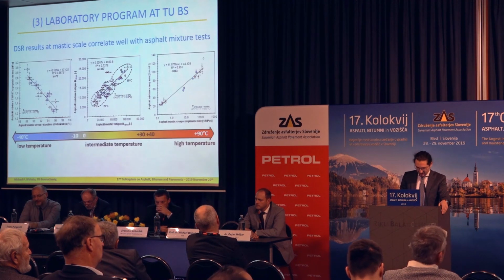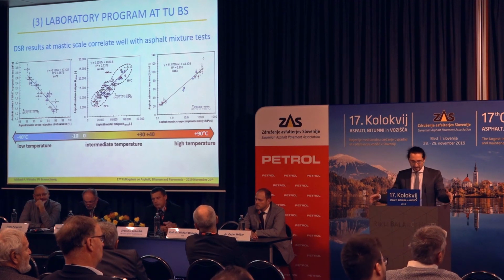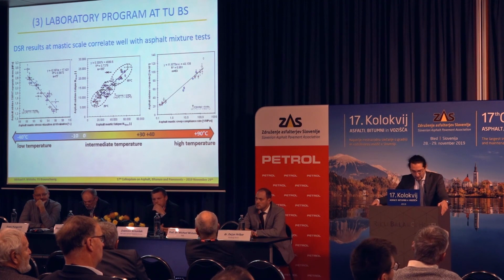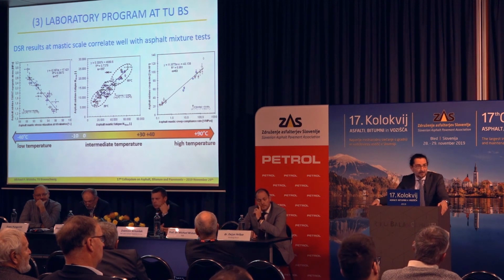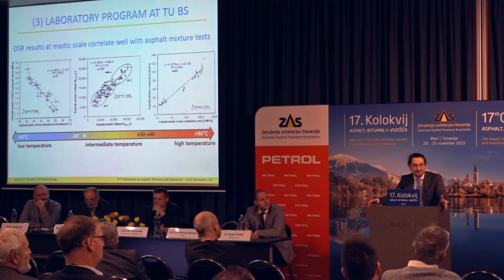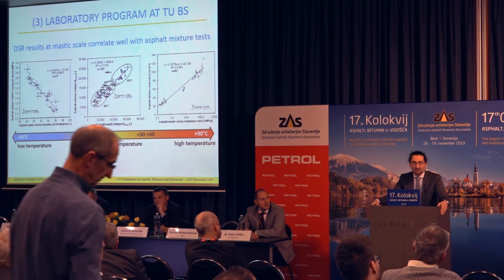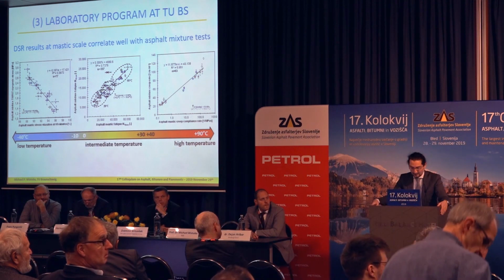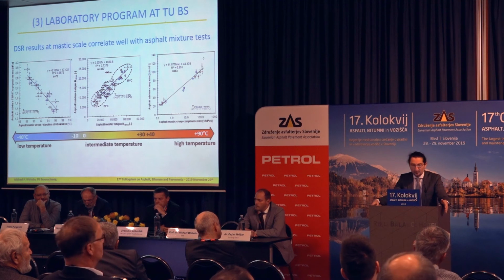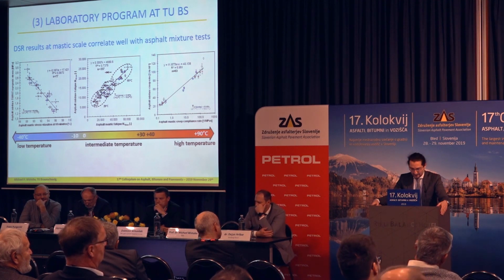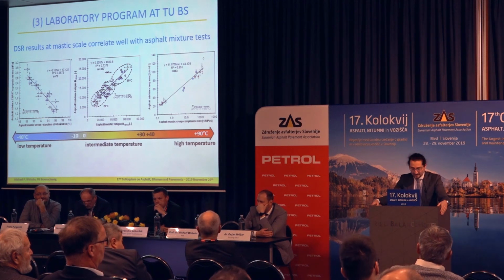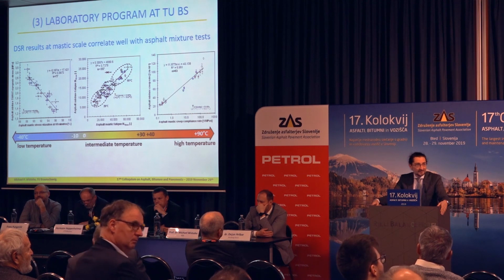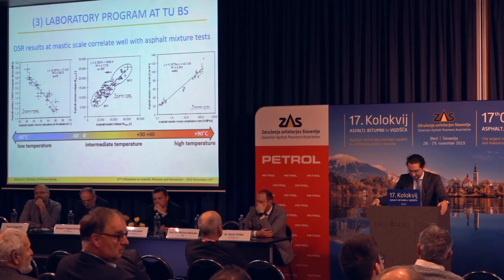We will see. But in general, at the moment, we found out that the DSR results really look good at the mastic scale. They correlate quite well. So it is possible for standardized asphalt mixture to predict performance in the laboratory by very easy tests, because these tests, I think at the moment, the test which takes the most time is the creep test, and this is done within, I think, 90 minutes. So they are very fast. These tests are very fast.